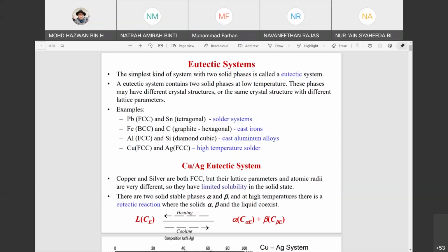melting temperature alloy. So if you still remember, the reason it is possible for a eutectic system to be established is because it didn't follow the Hume-Rothery rules. If it forms an isomorphous system, it means that these two elements follow the Hume-Rothery rules, and after that it will form a homogeneous system.